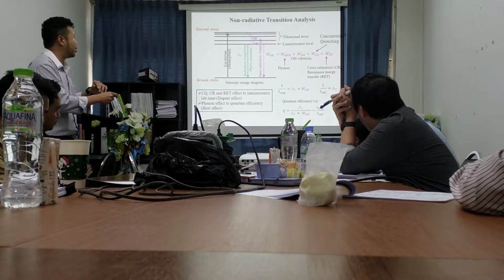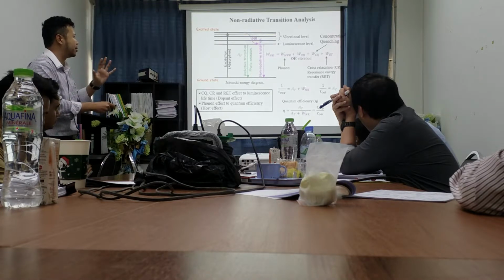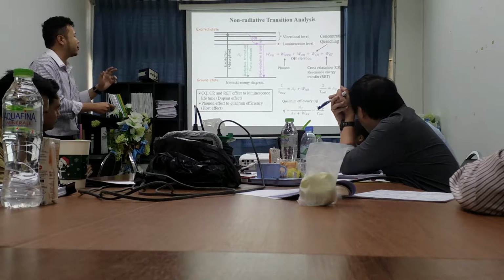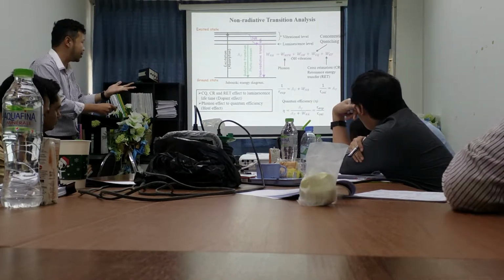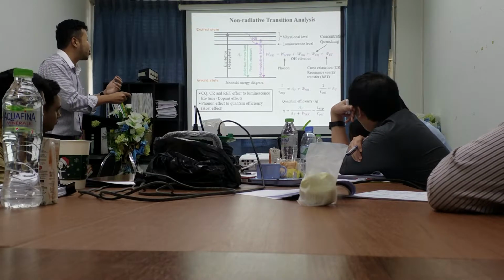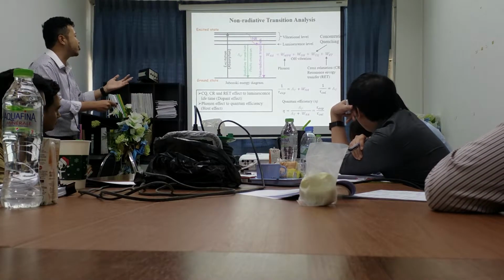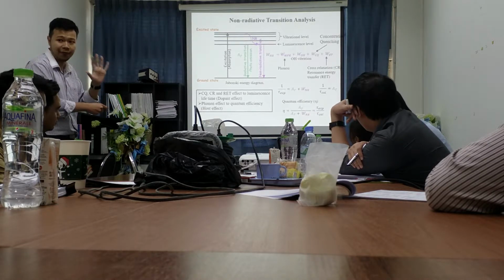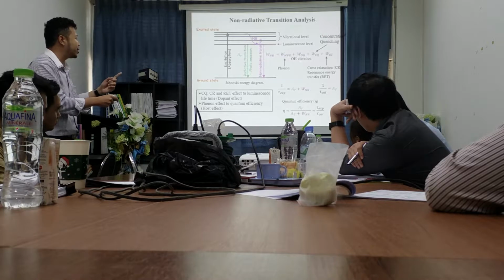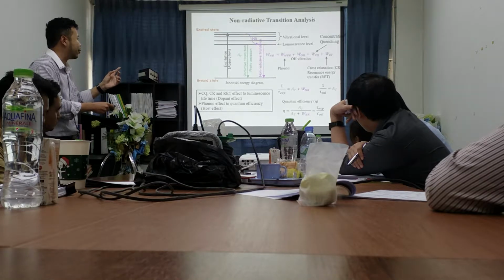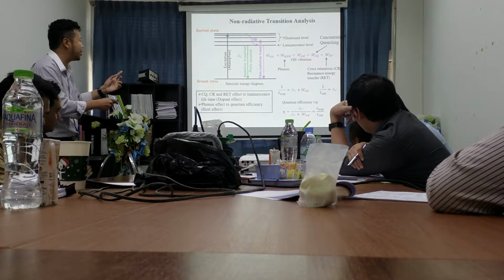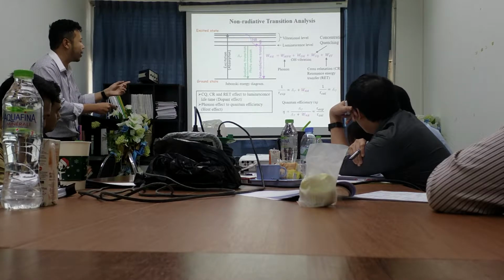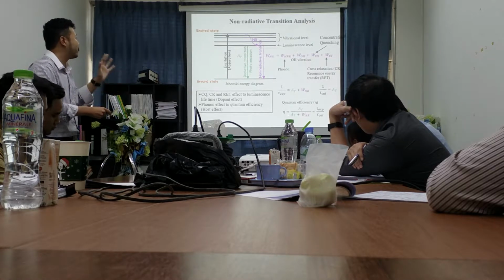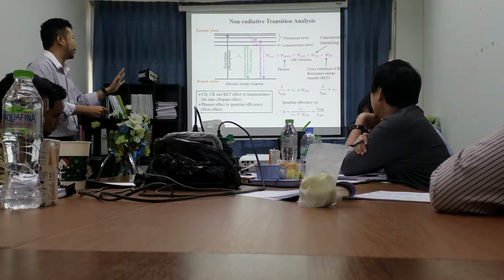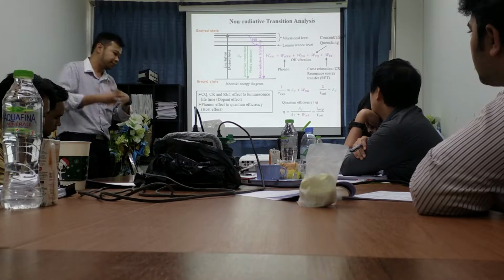And the non-radiative transition rate is related with the experimental lifetime that we measure from the measurement. That means concentration quenching, cross relaxation, or energy transfer affects our luminescence lifetime. Moreover, OH vibration and phonon vibration are also related with the quantum efficiency. You can see this is related with the WNR, and the WNR is related with the quantum efficiency. That means phonon vibration also affects the quantum efficiency. This affects my work.